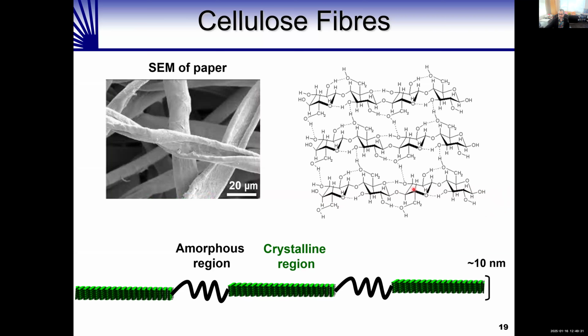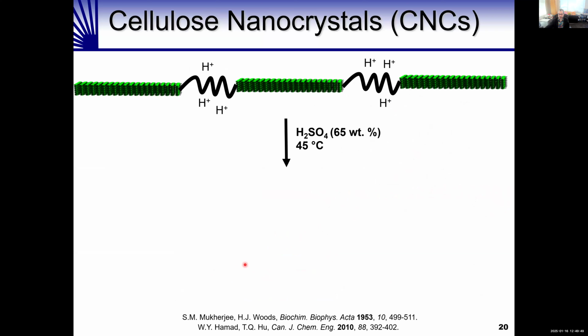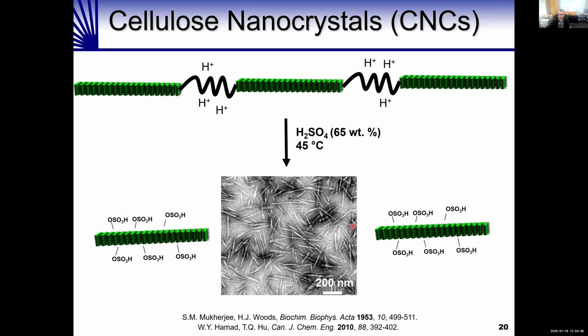When these chains of cellulose are hydrogen bonded, they form crystalline regions of cellulose. In a piece of paper, there are both crystalline, or organized, regions of cellulose and amorphous, or disordered, regions. But it was shown in the 1950s that if you take a piece of cotton or paper, which are mostly made of cellulose, and treat it with sulfuric acid under the right conditions, you can selectively hydrolyze away the amorphous regions and isolate these nanocrystals of cellulose. This is an electron micrograph of cellulose nanocrystals, and I'll show you that up close in a moment.